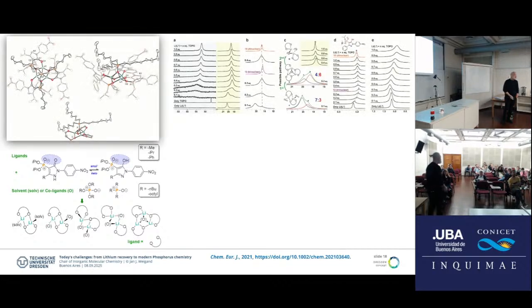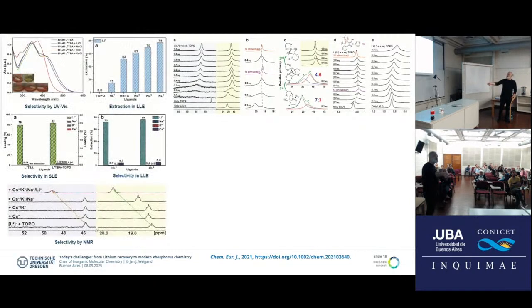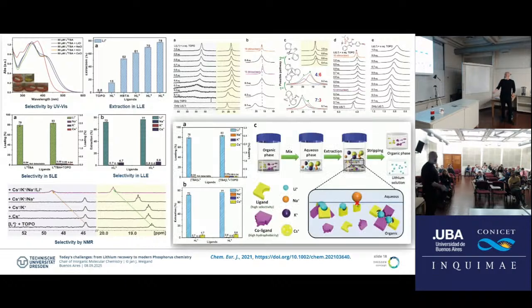And so we have a lot of different kinds of techniques. We looked into NMR speciation studies. I'm not going to go into detail. I refer to the paper if you're interested in this. We also looked into liquid-liquid extraction and solid liquid extraction, meaning you have just a salt or a solid material, and you just add the ligand in an organic solvent, and then you selectively only extract the lithium, and everything else remains in the solid state. And so with this, you see this is lithium, and you see the other ones like sodium, potassium, and even cesium, and there's almost no extraction in the SLE or in the liquid extraction.